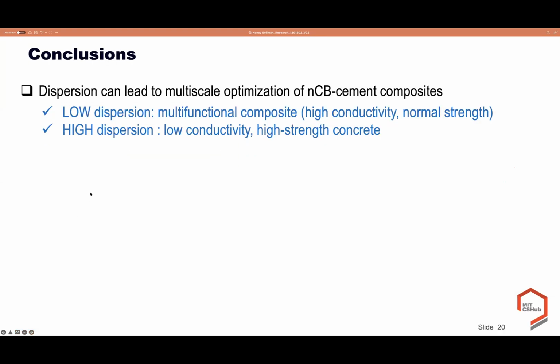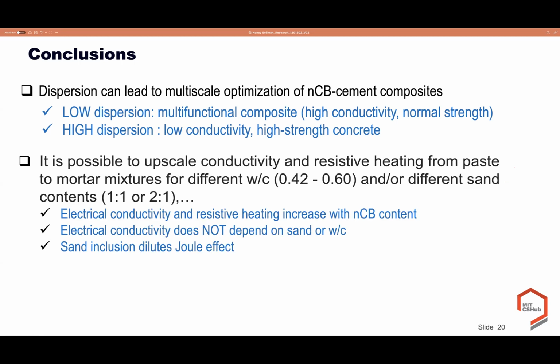From this, we can conclude this presentation: the dispersion can lead to multi-scale optimization of nanocarbon black. At low dispersion, we can achieve a multifunctional material with high conductivity and normal strength. While at high dispersion, we break the conductivity between nanocarbon black particles, but we can obtain high strength materials. Also, it is possible to upscale conductivity and resistive heating from the paste to the mortar. And what we observed is that electrical conductivity and resistive heating of the material increase with increasing nanocarbon black content. Electrical conductivity does not depend on water cement ratio, sand content, or any other material.